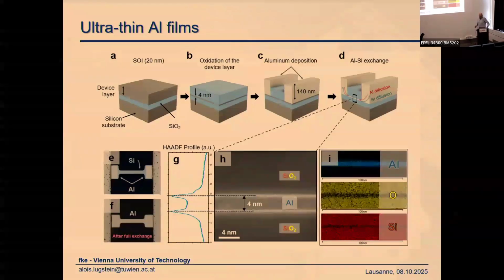So with this top-down approach, we can also now make thin sheets, starting with the silicon on insulator wafer. This can be easily thinned down by common oxidation, so that we end up with about, in this case, 4 nanometers thin silicon layer, which is automatically passivated by the oxide. And then we make these aluminum contacts, do the diffusion, and we end up with a very thin aluminum sheet.